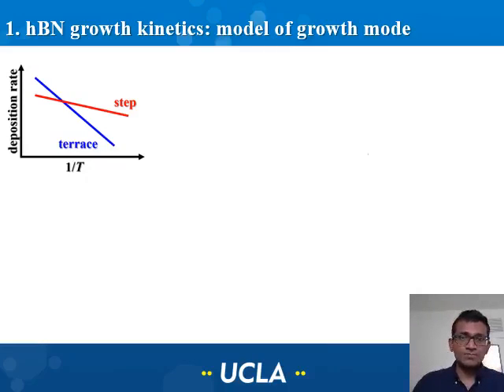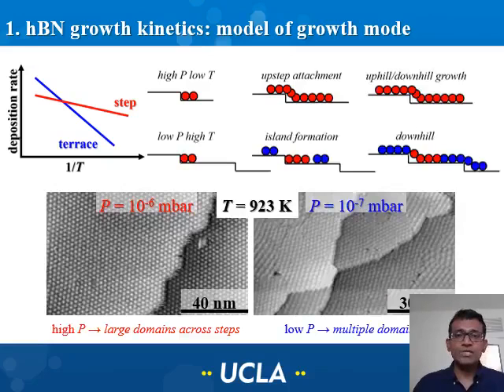Based on the experimental observations, we propose that the rates of deposition on the steps and on the terraces change as shown here, and there is a crossover at a certain temperature where the deposition rate on the terraces is higher than on the steps. And this leads to the formation of a monolayer via continuous growth across the steps or via preferentially downhill growth. And these are experimentally observed data where in our system we've been able to obtain relatively large single domains at higher fluxes and polydomain hexagonal boron nitride at lower fluxes. So these experimental results are consistent with what we think is happening in our experiments.